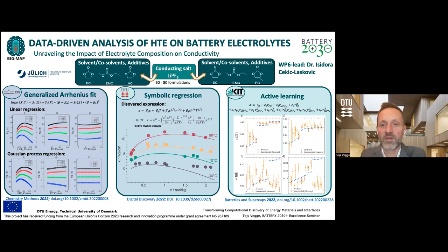So coupling in different machine learning techniques, either to find simple generalized models for Arrhenius fits to predict the performance or the metrics of the electrolytes, or in another recent collaboration, actually trying to deduce, learning the fundamental equations of the electrolyte diffusion. So given data from about 1,200 experimentally acquired data points at different temperatures, you were able to use symbolic regression to deduce the governing equations for the transport properties. The last example here is for an active learning framework done together with KIT, only using single data points to predict the next experiment to be performed.